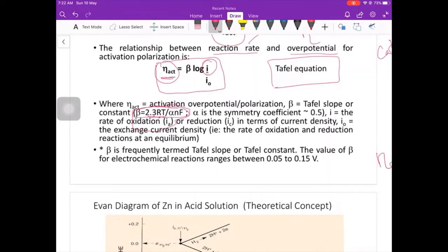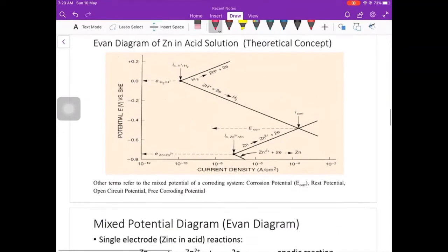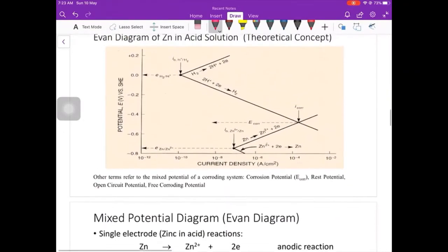This is the formula: 2.3 times R, the gas ideal constant, times T, temperature in Kelvin. This is alpha. Alpha is the symmetry coefficient, normally 0.5. And n is the number of electrons, F the Faraday constant. Right? So normally beta, the Tafel slope, is between 0.05 to 0.15 volt per decade.